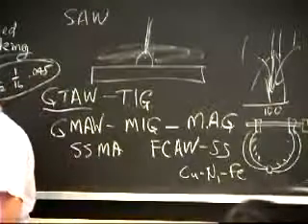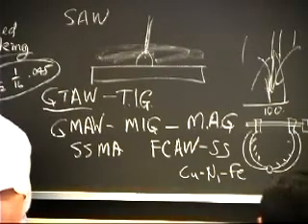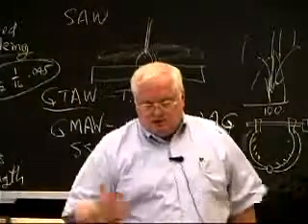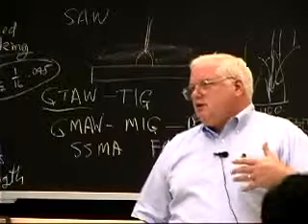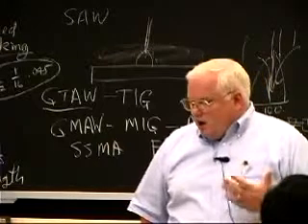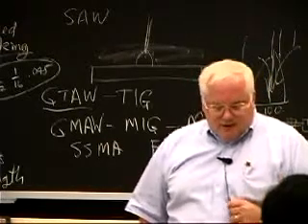Whereas the actual part that was holding it, that contained the hydrogen, was a low-strength steel, didn't have very high stresses, but when you put this hardened steel roll pin inside the hole, under stress, it cracked. So in that case, the hydrogen may have remained there for a few weeks or even a couple of months under those conditions. The hydrogen usually will relieve itself over time.